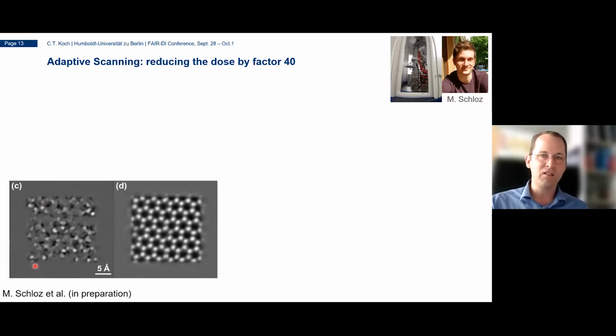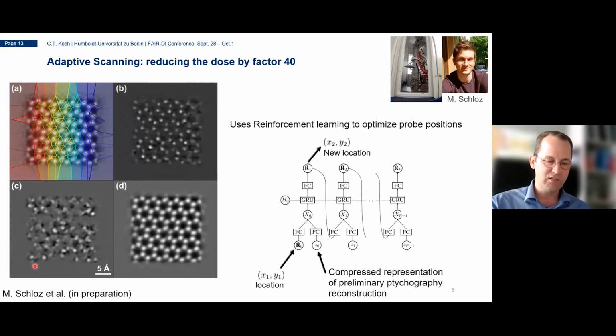But if you now let the computer learn while you're doing the acquisition to position your probes more smartly, and this is a pre-trained network that has been trained with experimental data, it starts first randomly, but then it improves and gets better and better data. And of course, this has to be pre-trained. I mean, this acquisition here was relatively fast, but the information about how to interpret these diffraction patterns and so on had to actually be pre-trained and took 2 weeks.